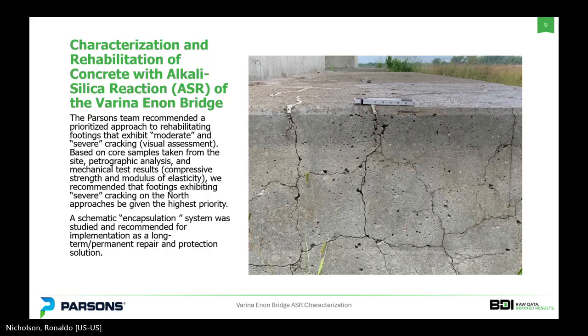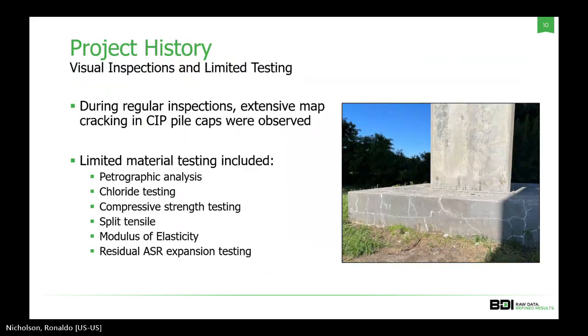Yep. Thank you, Nick. So now we'll go over some of the project history and some initial investigations. So like Nick said, the Parsons team recommended a prioritized approach, first to look at the moderate and severe cracked pile caps based on some of the core samples taken from the initial investigation, some petrographic analysis, material testing, that kind of stuff. They did recommend that at least the severely cracked pile caps in the north approach be given the highest priority, and again, the goal would be to extend the life by doing some sort of repair. And in this case, the schematic encapsulation system was studied and recommended for implementation as a long-term solution.